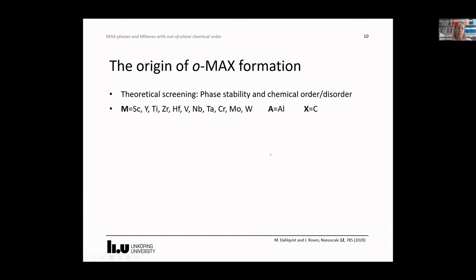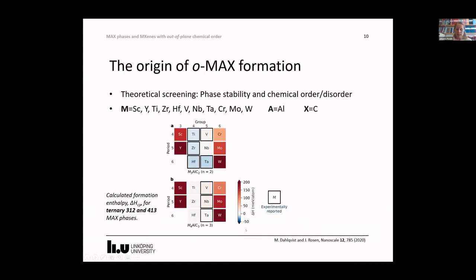At first, we look at the stability of the pure ternaries, where the background color represents the stability. It should be white or more bluish if the material is predicted stable. And the square shows if the phase has been experimentally reported or not. And this is shown for 312 and 413. So, thermodynamically stable or close to stable MAX phases for 312 and 413 are found for M elements from group 4 and 5, while MAX phases from group 3 and 6 are not stable. And all the experimentally known phases are indeed found in group 4 and 5. What is important to note is that the niobium 312 and the titanium, zirconium, and hafnium 413 are also predicted to be stable MAX phases, but are yet to be experimentally discovered.